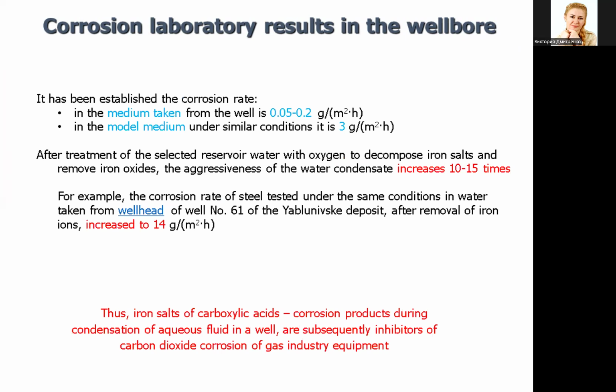After treatment of the selected reservoir water with oxygen to decompose iron salts and remove iron oxides, the aggressiveness of the water condensate increases 10–15 times. For example, the corrosion rate of steel tested under the same conditions in water taken from the wellhead of well number 61 of the Yablonivsky deposit, after removal of iron ions, increased to 14 grams per square meter per hour. The iron salts of carboxylic acids, which are corrosion products during condensation of aqueous fluids in a well, are subsequently inhibitors of carbon dioxide corrosion of gas industry equipment.